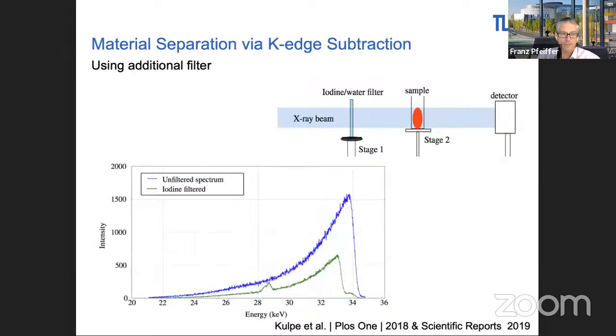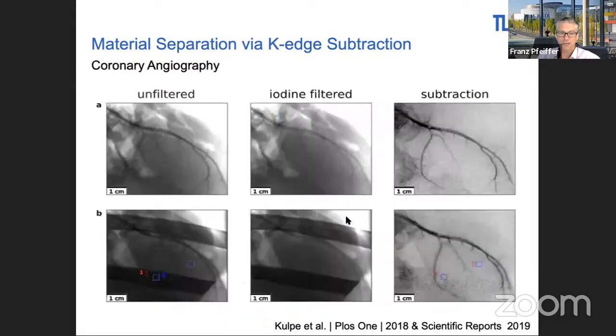You can elaborate on that a bit further and do K-edge subtraction imaging, in this case by adding an additional filter, which has the K-edge exactly where the sample has it, and then you end up with two spectra, which you can subtract. And then you can also filter out other overlaying components. So these are also mock-up experiments where you have some ribs, strongly absorbing bone, in front of this heart with the contrast agents. This you can get completely rid of by this K-edge subtraction imaging and still then see the artery. So these are investigations that basically explore potential medical applications in future, because it has been done at synchrotron sources before.